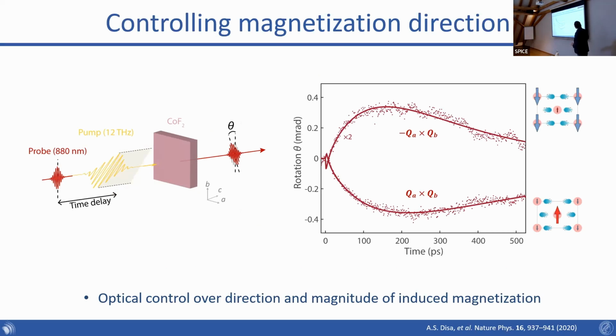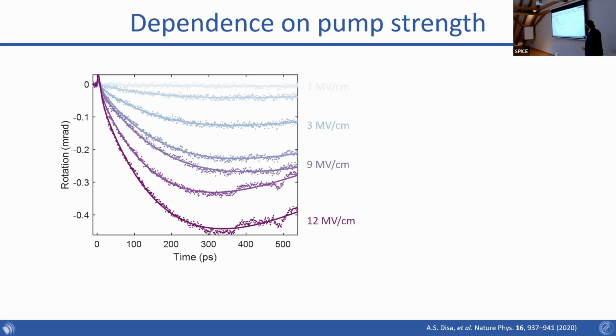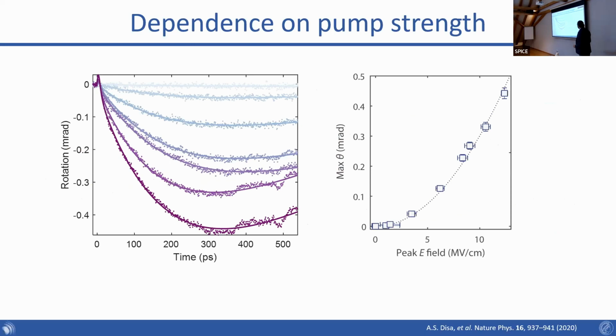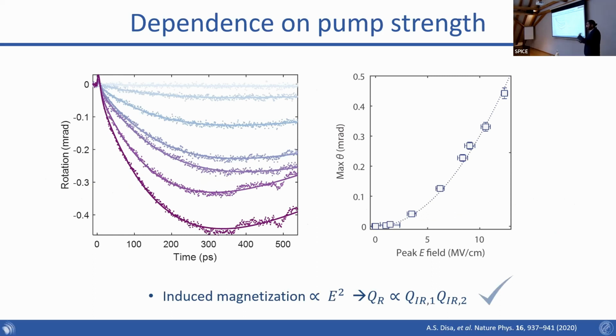Okay. Now we can also see what happens when I crank up the field strength. I go from, let's say, 1 megavolt per centimeter up to 12, which is the best that we can achieve right now at 12 terahertz. And you can see, first of all, that the maximum rotation angle scales quadratically with the field, which is what we would expect based on the excitation of these two phonon modes. So that's good. We also find that it has a resonance in the wavelength dependence right at the phonon frequency. And so now we can kind of construct a picture of what might be happening in terms of the dynamics and the driving of this particular system.